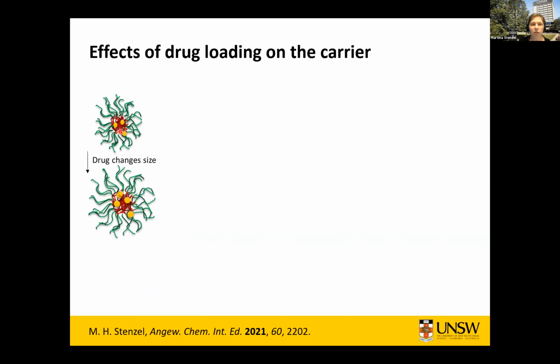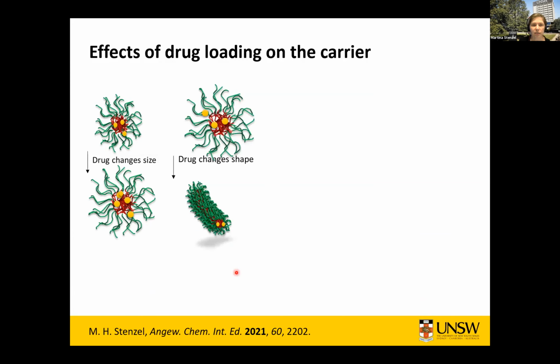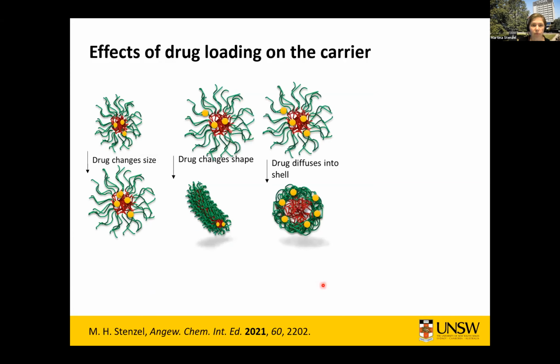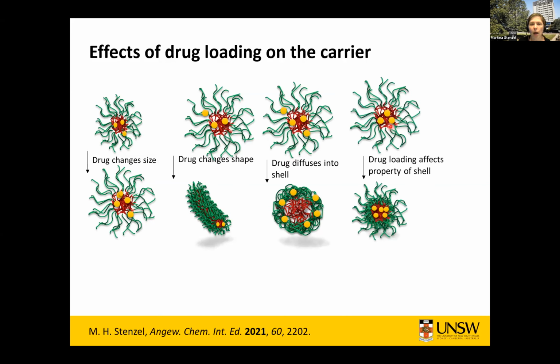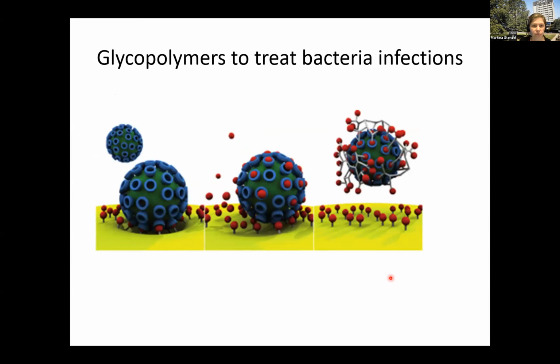So then in reality, there are a lot of effects the drug might display on the nanoparticle. In the simplest case, loading drugs might just change the size. Sometimes it changes the shape. We found occasionally that the drug doesn't stay in the core, it might diffuse into the shell. Or the drug simply affects the property of the shell. And of course, in the next step, this will influence how these nanoparticles absorb proteins. So some of them absorb less proteins than the other ones.